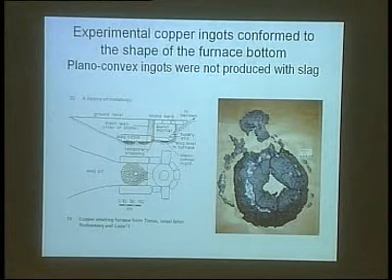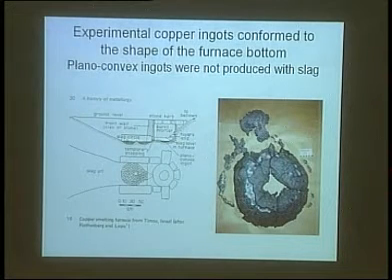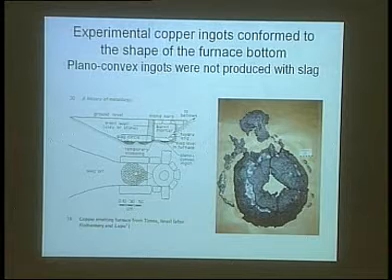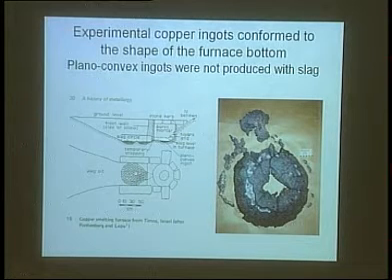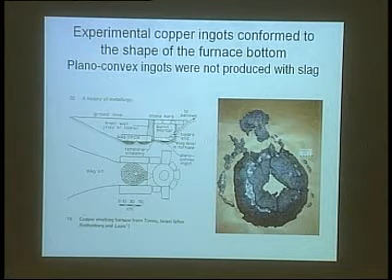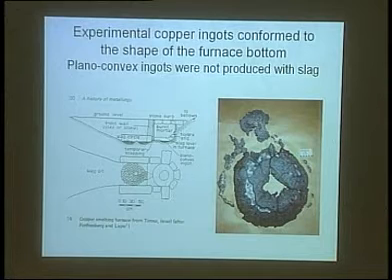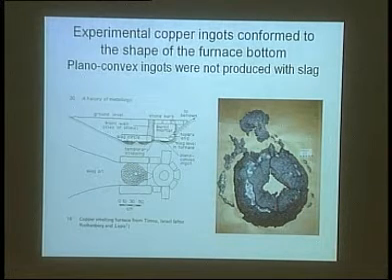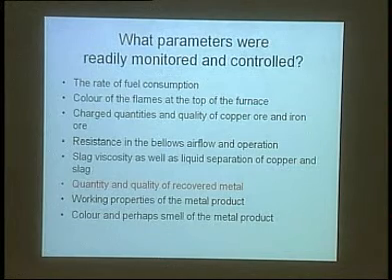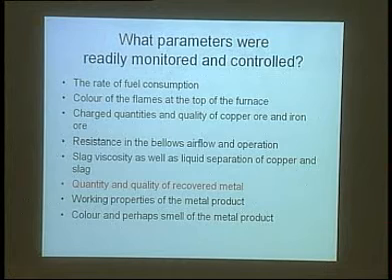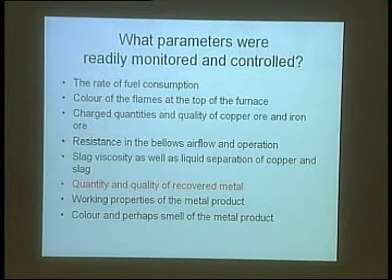So again, on balance, this is the type of product that we produce from the furnace. Here's this ingot that I showed you, and the slag. There was some copper that ran out with this as well, but we don't find these structures. So the copper was probably about 2 kilos per furnace. There are many more details, and we really worked on this and used it over the years.